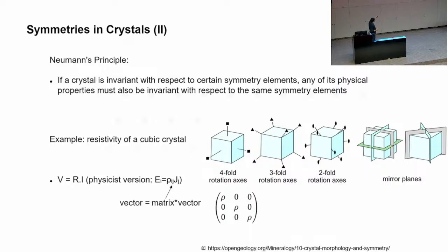But now we can understand the symmetry of this matrix by just applying the symmetry operations of the crystal. And it turns out that for the cubic symmetries, we end up with only one parameter, which is the resistivity of this cubic material. Now it doesn't matter in which direction of the cube you measure the resistivity, you must always get the same value. So it doesn't matter if you measure along the diagonal or along the edge here, you must get the same thing. Symmetry dictates that it has to be the same. So symmetry is something very powerful. We can really make very hard statements about the properties of matter.